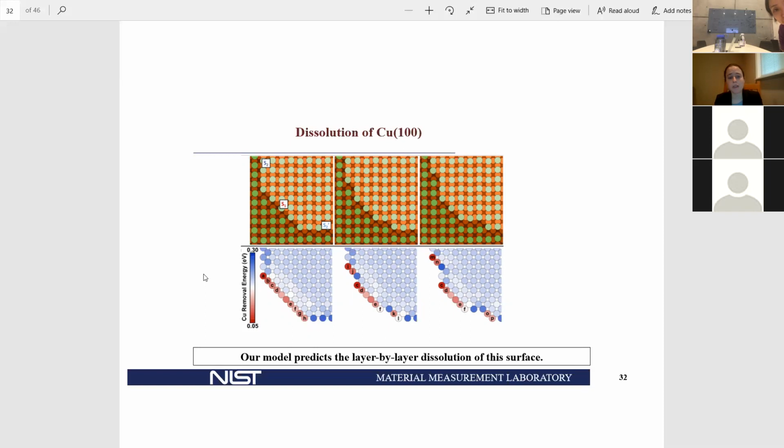If you're looking at metals, there's the potential for getting in trouble, not only because of the electron transfer, but also because for a lot of metals, it looks like there's more going on than just a double layer. It seems clear that for a number of metal surfaces, even platinum 111, you have cations that are explicitly interacting with the surface. If you're not describing these effects, you're probably not going to be able to describe the surface at all, whether it's with a continuum model or with full out AIMD.